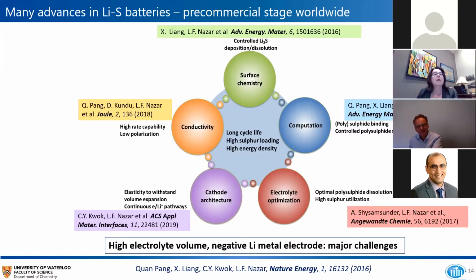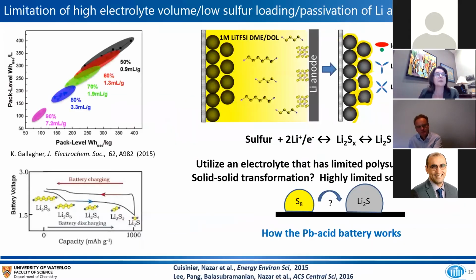So since the paper long ago, there has been an awful lot of effort, both by us and many hundreds of thousands of groups around the world. And so I can't summarize them all here. We did write a review article on it, and this just shows a few examples from our group. And really one can divide the issues at the cathode into developing better surface chemistry to control this polysulfide dissolution, improving the electronic conductivity of the cathode to allow for high rate capability, improving the architecture with binders to effectively allow for this elastic expansion and contraction, using computation to try to guide new materials for the cathode, and especially electrolyte optimization, which is necessary in order to sustain the negative electrode and also to solve the problem of high electrolyte volumes that I'll talk about on the next slide. So the next couple of slides focus on the electrolyte issue because I don't have time to discuss all the rest of it.